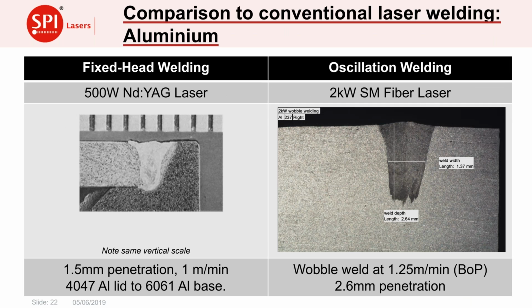So I just wanted to show you an example of that, quick aluminium welding. Something that we've done previously with a pulse YAG laser on the left, and then, admittedly, a higher power single mode fiber laser on the right. We've got a much bigger penetration for a similar speed. So we've nearly doubled the penetration, and we've got a wider weld. But we can see that with the oscillation welding, we can produce even a weld profile that's similar to that from a YAG laser if we want to.